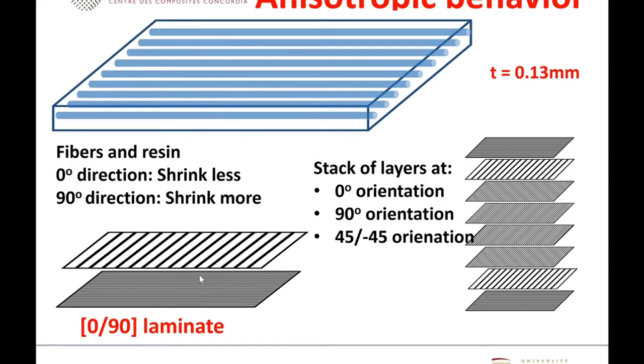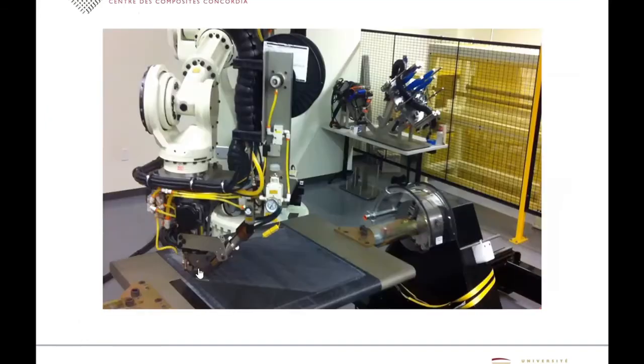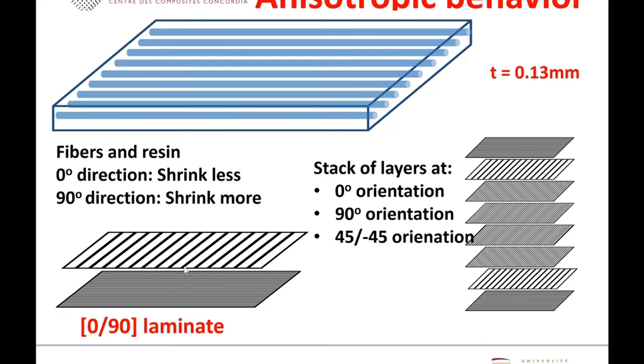Now usually the way that people make the composite, because it's made out of epoxy resin, you have to bring it to high temperature, like 180 degrees centigrade, to cure it. That means you have to cure the resin to change it from a liquid state to a solid state. So at the beginning, you have something that is flat, and then you heat it up and cure the resin. When it's cured at 180 degrees centigrade, and the thing is rigid and bound together very well, then you cool it down. When you cool it down, again, due to the difference in expansion or contraction along the different directions, this will make a curve. It will curve up and make a curved structure.